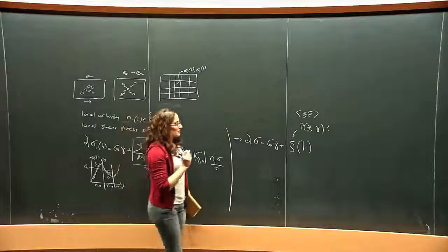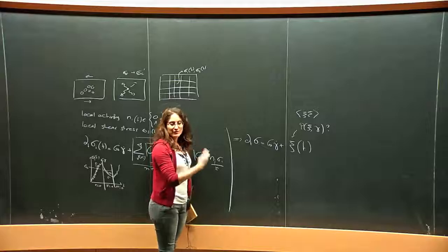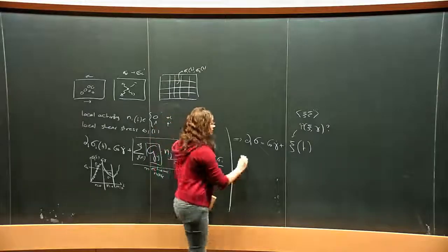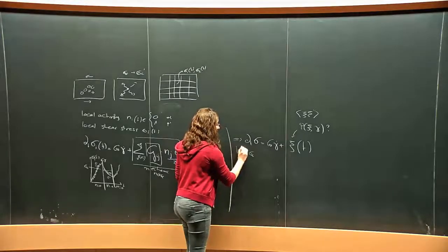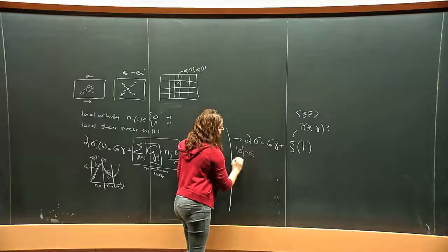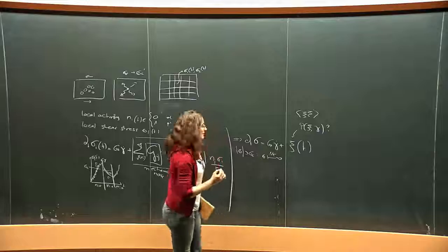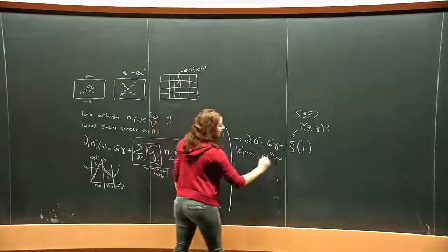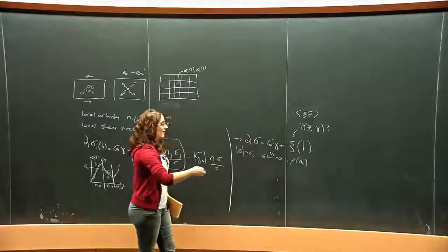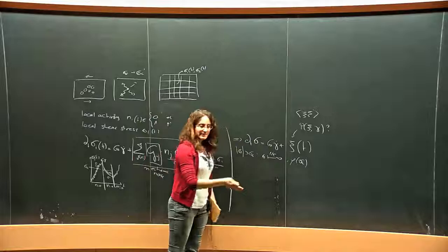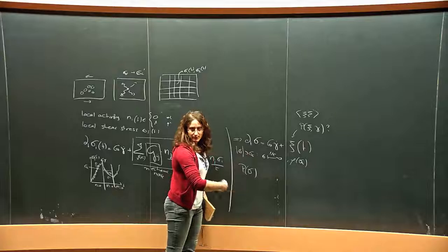But I want just to emphasize one point, that also what is important is to allow, in the model, the change of the barriers. For instance, in the original Hébraud-Lequeux model, you assume that you have a given local yield stress, which is fixed all the time, and you say that when the stress is above, then your stress will relax to zero with a given rate, for instance. Now, if you allow a distribution of local yield stress that you pick up at each rearrangement, on top of that, already in the steady state, you can follow the fluctuation of stress with the mean stress and predict the flow curve.